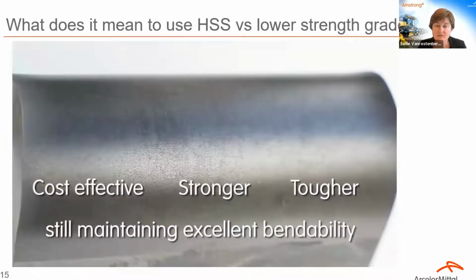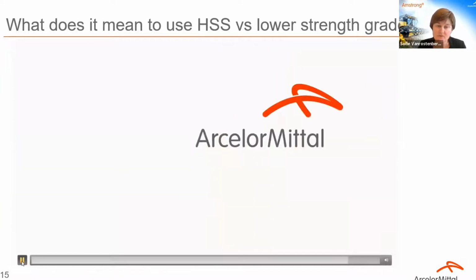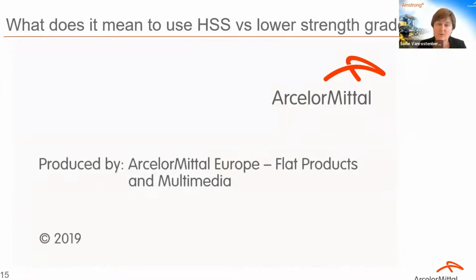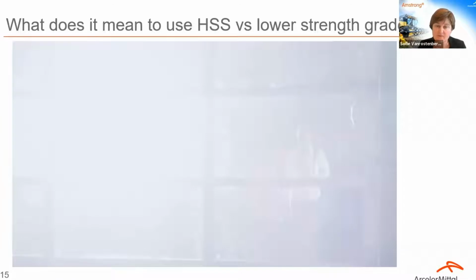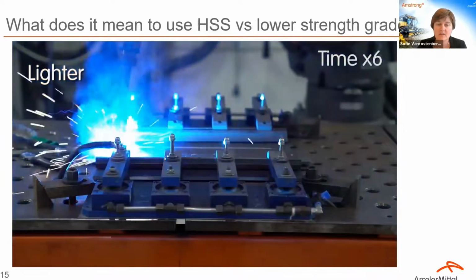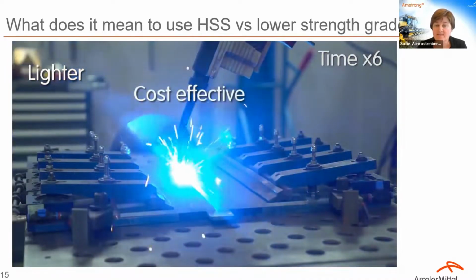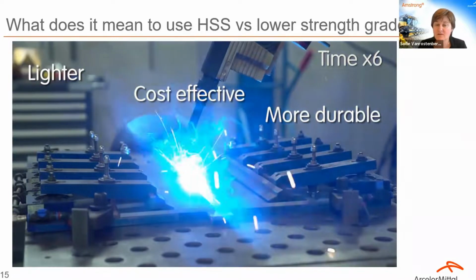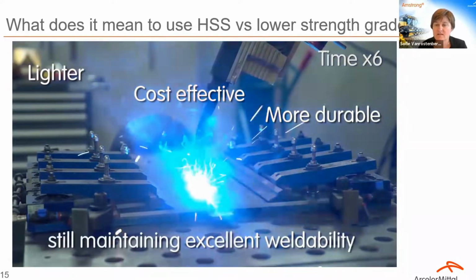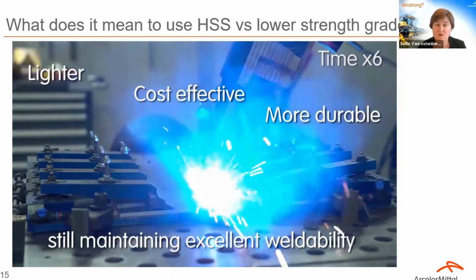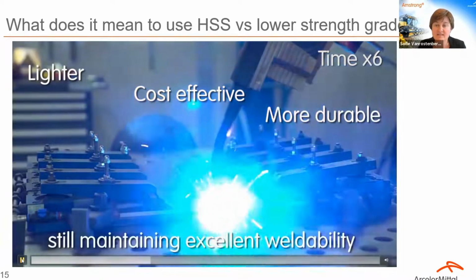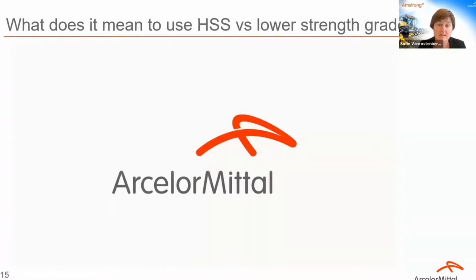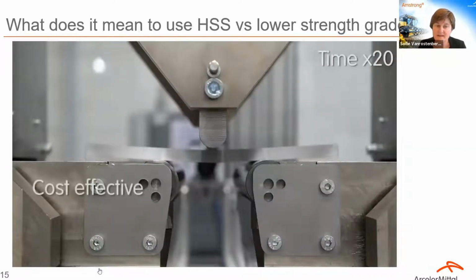When welding high-strength steels, care should be taken to limit the heat input, and we can provide you a suitable process window for welding, allowing you to select the best welding parameters using your welding equipment. Of course, we help you to choose a suitable filler wire, matching or overmatching the strength of the base material. When shaping a part, the bending radius and the bending gap is of utmost importance. So bending guidelines strongly depend on the thickness and should be aligned with the dimensions and the mechanical properties of the chosen grade, thus already anticipating springback.